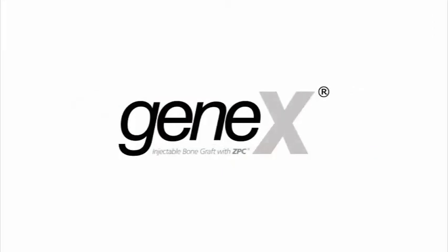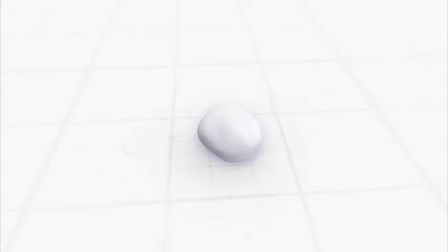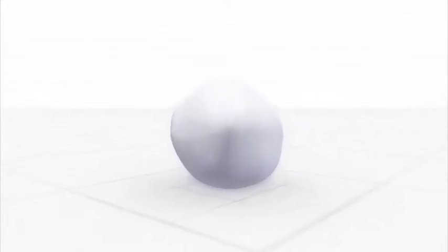Gene X is a unique biphasic bone graft which possesses a controlled, reproducible negative surface charge. It is hydrophilic, has a physiologic pH, and is fully resorbed and replaced by bone. These properties make Gene X a huge leap forward in bone graft engineering.